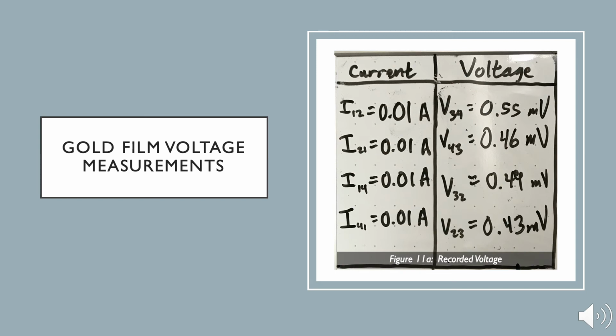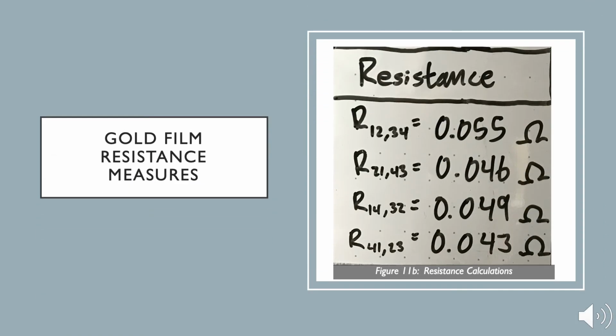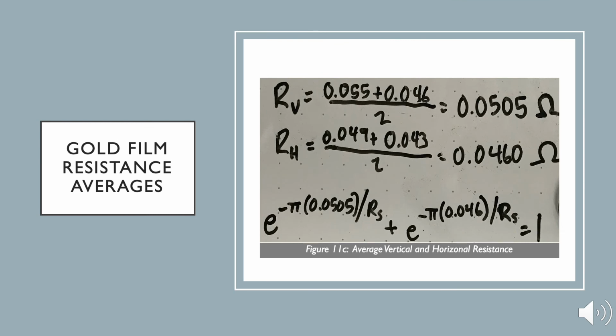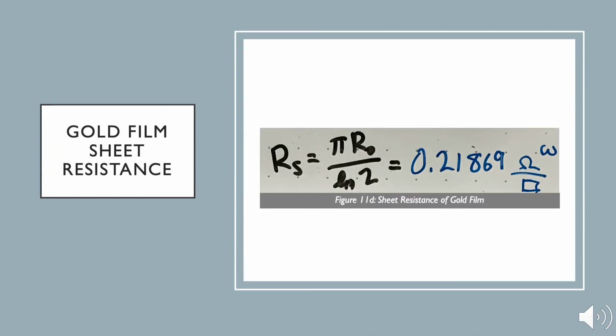As seen in Figure 11a, we first measured the voltages resulting from a 10 milliamp current using the 4-point probe method. Then, in Figure 11b, we calculated resistance by approximating the relationship between voltage and current as linear, and used Ohm's law manipulation, resistance equals voltage over current. We then averaged them in Figure 11c and used van der Pauw's sheet resistance equation to calculate sheet resistance. As you can see, van der Pauw's equations are very mathematically complex, but he also had a simplification of this equation, which results in an accurate approximation, which is how we determine the sheet resistance of the gold film in Figure 11d.